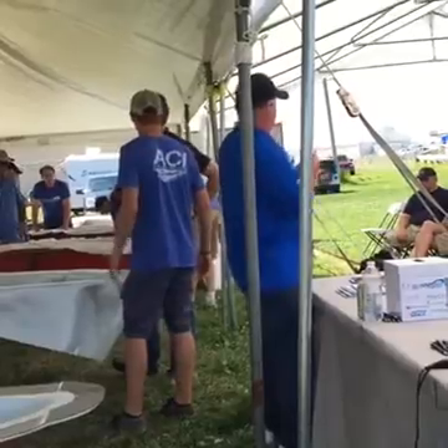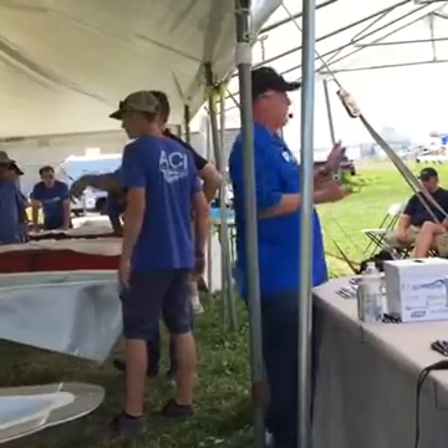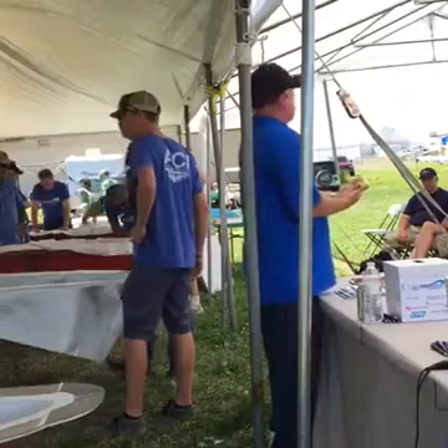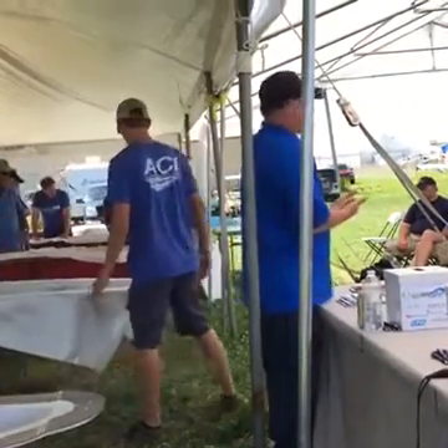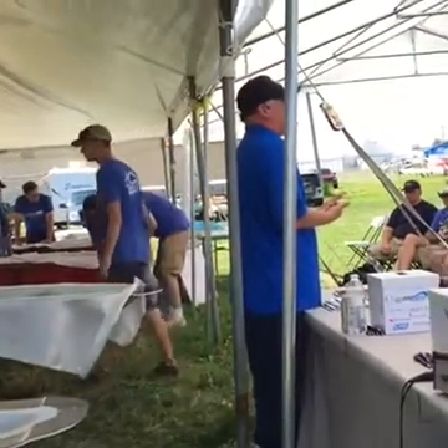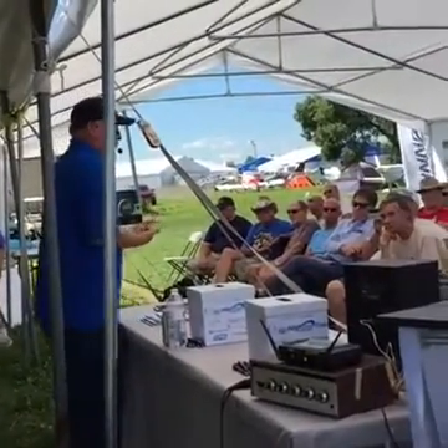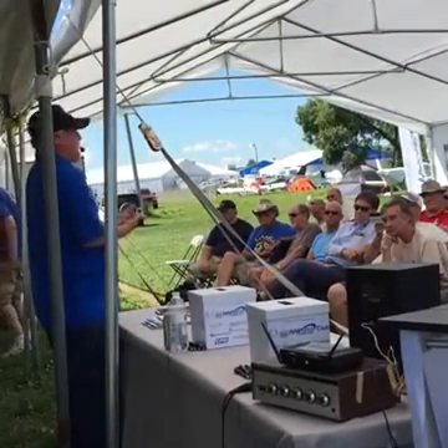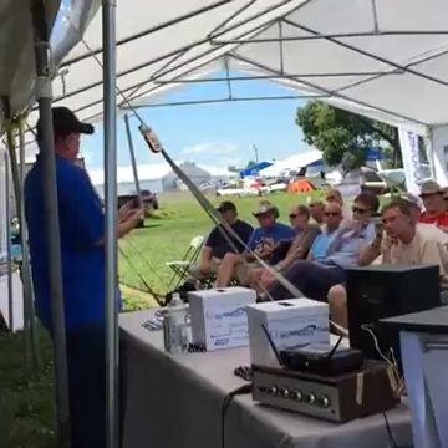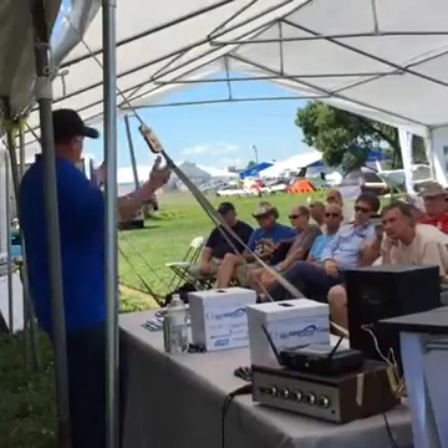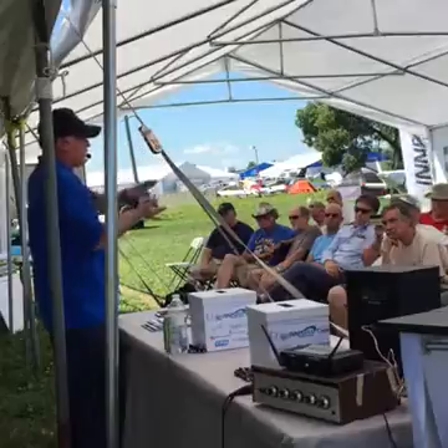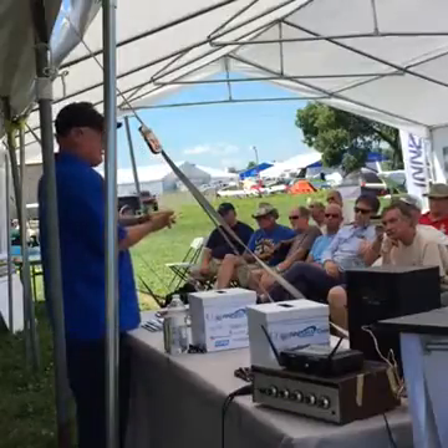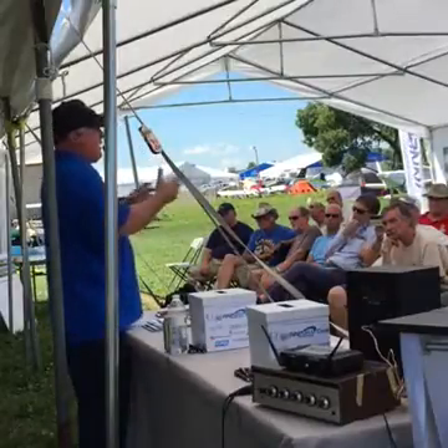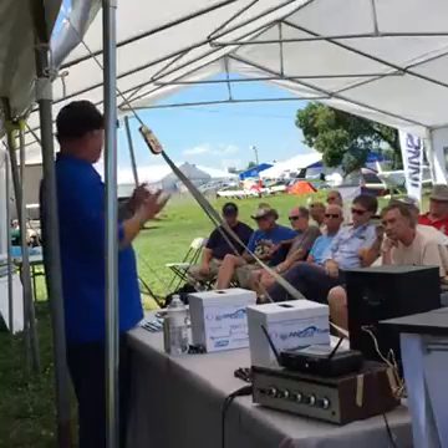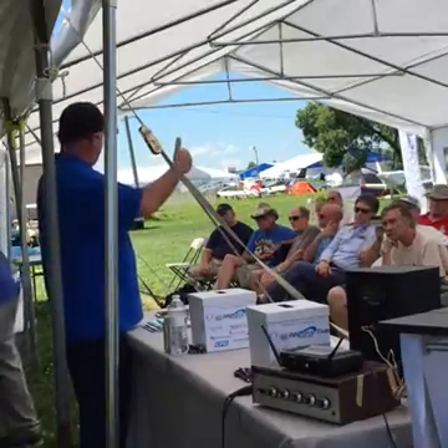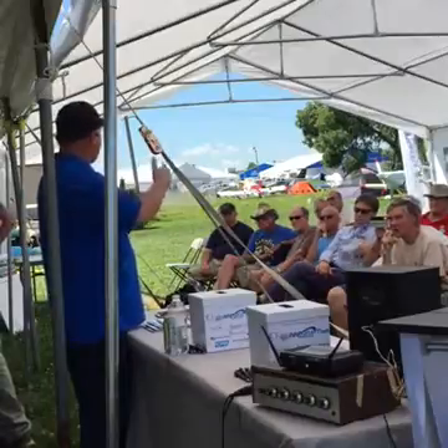Using 2 bags allows you to use differential pressure. If you want 100% consolidation of the part, but you can only pull, say, 23 inches of mercury before your resin boils, you can do it. You can actually pull your resin at 23 inches of mercury, and maintain atmospheric pressure as the pressure against the bag itself. That's the 2 differences. So if you're on epoxy, then you can do the same thing.